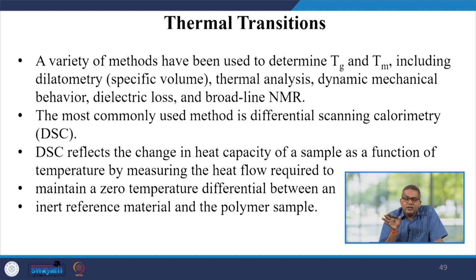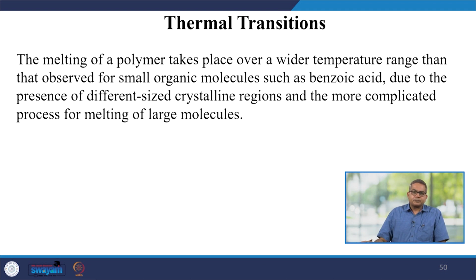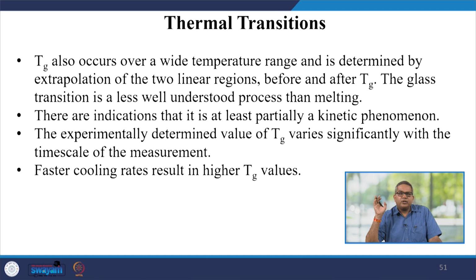This reflects the change in the heat capacity of a sample as a function of temperature by measuring the heat flow required to maintain the zero temperature differential between an inert reference material and a polymeric material. The melting of a polymer takes place over a wider temperature range than that observed for a small organic molecule such as benzoic acid, due to the presence of different size crystalline regions and a more complicated process for melting of large molecules.